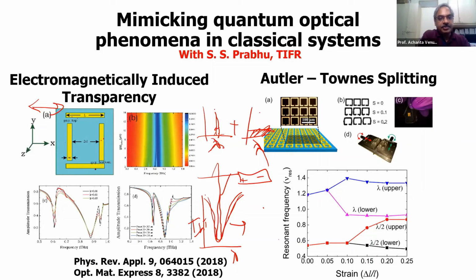Now, if you put another dipole underneath, right? So now this one and this one are both going to excite a dipole in this. So the incident electric field polarization is going to excite a dipole in the top and the bottom rods. So each one is going to induce the same field, so they just cancel out if the gap between these two is exactly the same. But if we make these gaps asymmetric, so the top gap is more than the bottom gap, for example, then it's a non-symmetric, an asymmetric system.